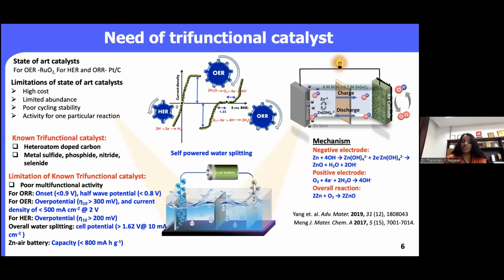That means a catalyst which can perform the hydrogen evolution reaction along with the oxygen evolution reaction. In addition to this, we need the oxygen reduction reaction, because we need to develop the air cathode. To do this, we need an oxygen bifunctional catalyst. As I said, the state-of-the-art catalysts remain ruthenium oxide for the oxygen evolution reaction and platinum carbon for both the hydrogen evolution as well as the oxygen reduction reaction.